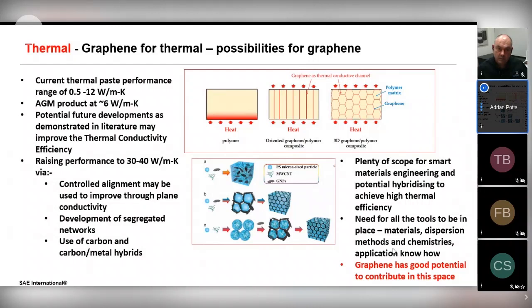So things that we're looking at currently: controlled alignment of graphene to be able to create planar structures with that material to enhance thermal conductivity further, as we see in the middle of the top right little diagram, and then segregated networks or domains of materials, whereby we can segregate areas of graphene for higher thermal conductivity. And then also engineering to produce hybrids, so combining with other materials to enhance the performance yet further. So we see a great need, but we see a great opportunity also for graphene in this space to be able to contribute through materials engineering to create some great solutions for thermal performance with graphene nanoplatelets.